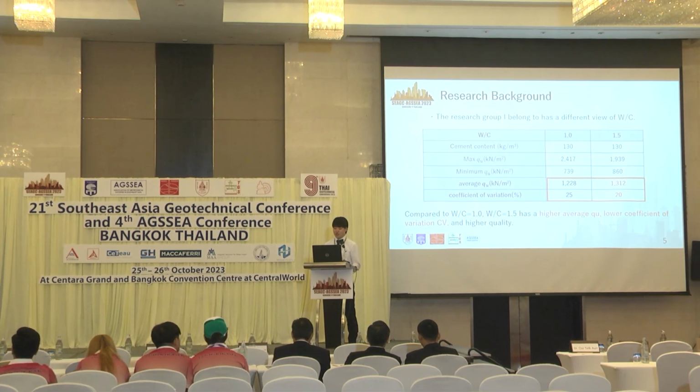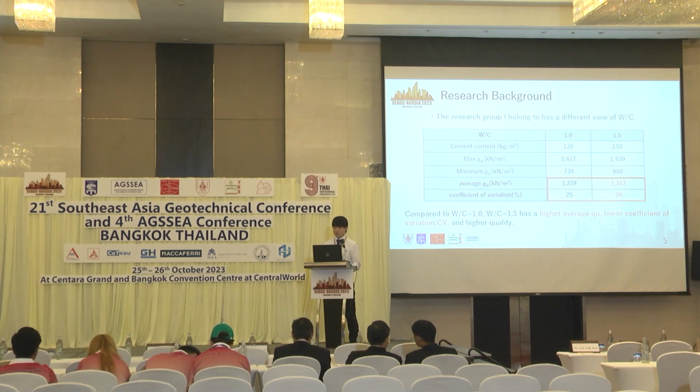However, the research group I belong to has a different view on W/C. This table shows data from actual test construction. Compared to W/C 1.0, W/C 1.5 has a higher average QU, lower coefficient of variation, and higher quality.